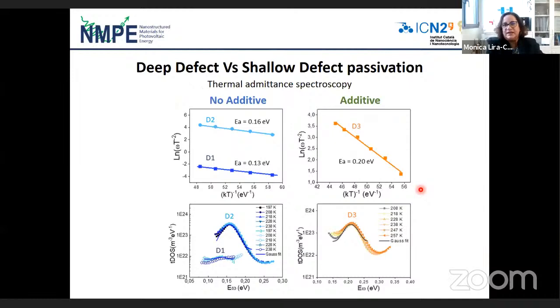What we did is analysis by thermal admittance spectroscopy, which tells us exactly if we are working with deep defect or shallow defect passivation. You can see here in blue the halide perovskite with no additive, and in orange the halide perovskite with the additive. You can clearly see that when we pass from one to the other, on this curve you can see deep defects here. D2 is deep defects, and D1 is shallow defects.